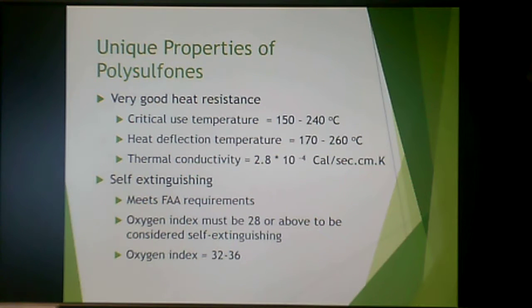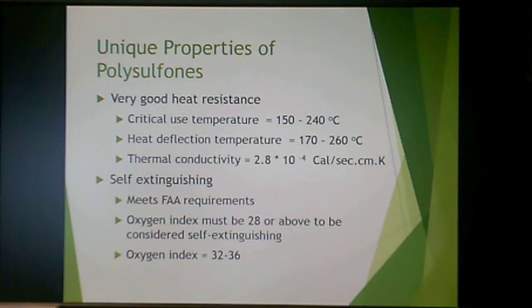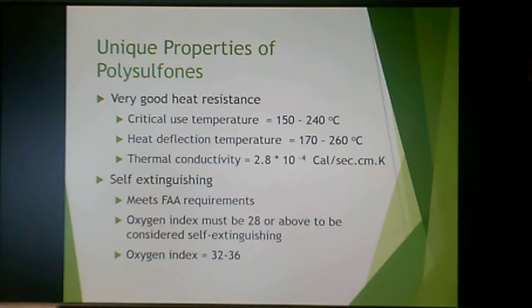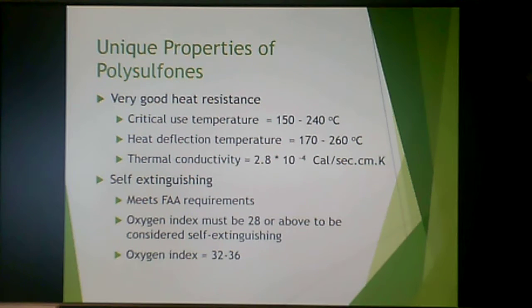Polysulfone meets the FAA requirements for being self-extinguishing. The FAA requires an oxygen index of 28 or above. For the purposes of this course I typically ask that it be 21 or 22, but the FAA requires 28 or above. The oxygen index of polysulfones ranges from 32 to 36 depending on the specific monomers used to make the polymer.